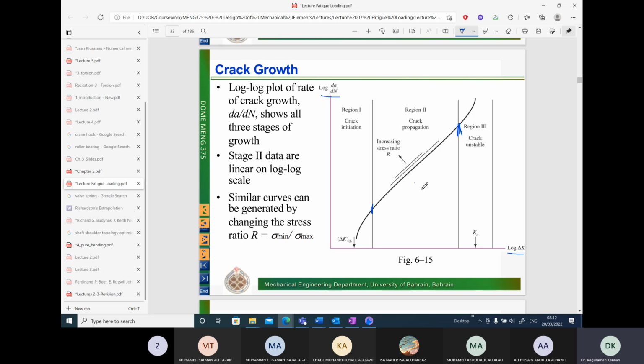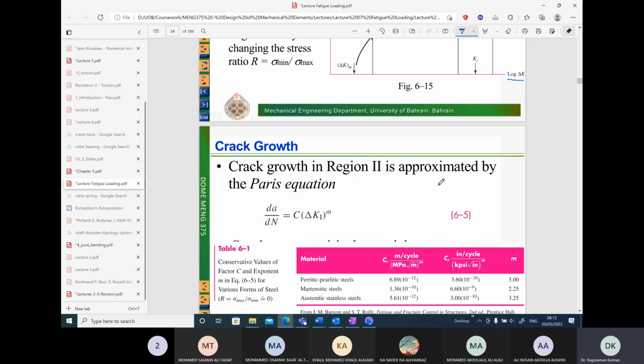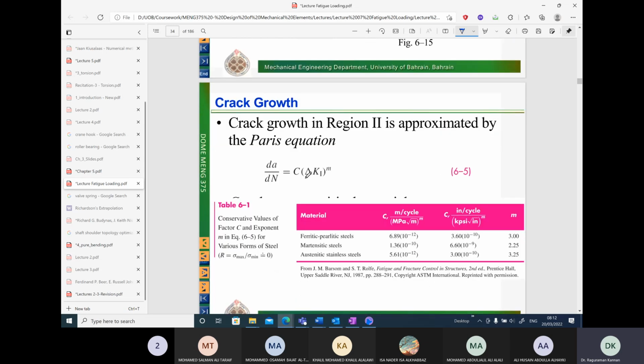Okay, so now based upon this graph, since this is a constant slope line, we can obtain an empirical relationship between dA over dN and delta K. And the empirical relationship, based upon the log plots, we can get two constants. One is the exponent, one is the constant value, connecting your rate of growth of crack length to your delta K values. So this gives you an equation which is called the Paris equation. Finally, you will be using this particular equation for solving problems.